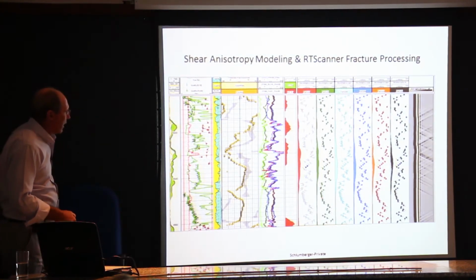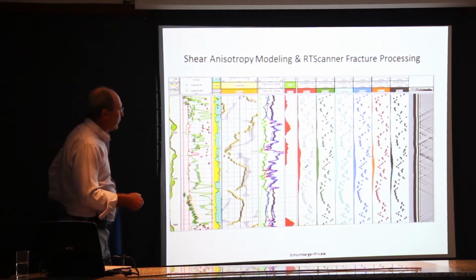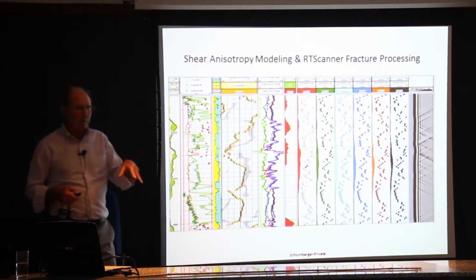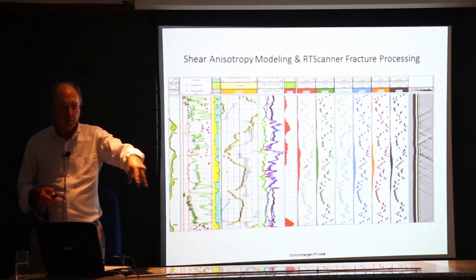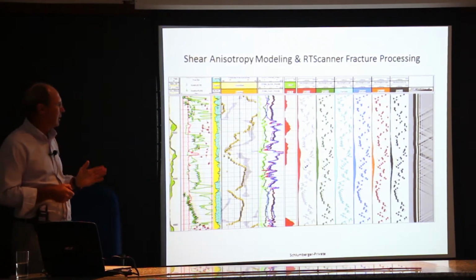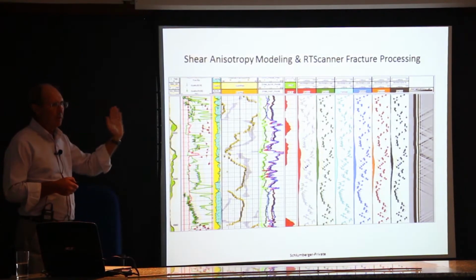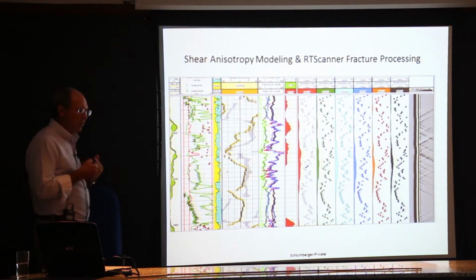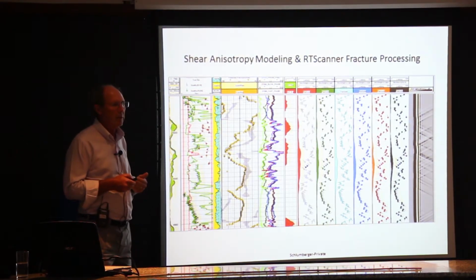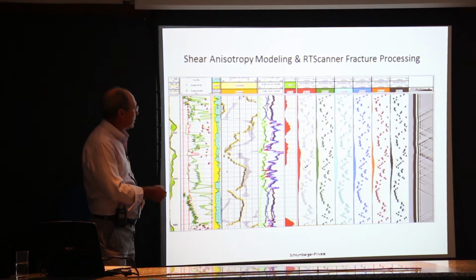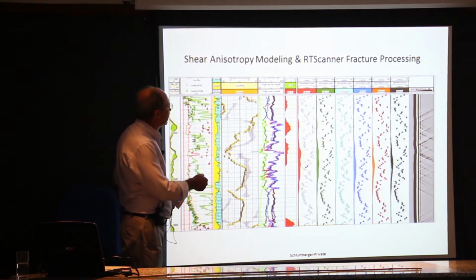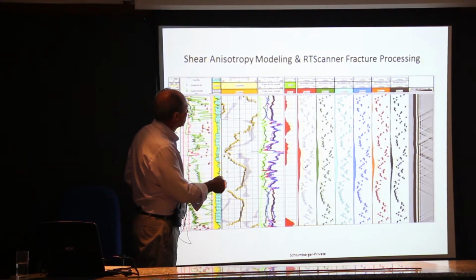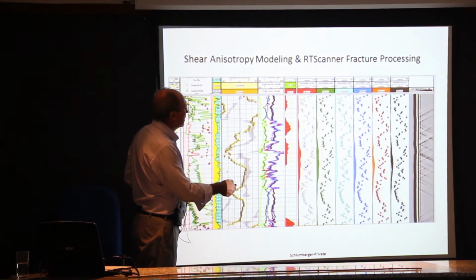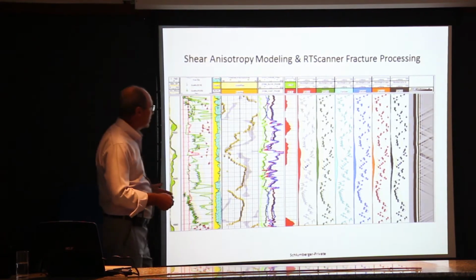And the next step is, if we combine this idea where it's called four-component rotation, where you rotate the fast and slow shear to get the ideal orientation of the true fast and the true slow, you can do the same thing with the 3D resistivity tool, and that's what we've done here. And with the resistivity tool, we start out with, I think this is about a 15-inch, and then we're moving to 20 inches, 25, 30. Finally, we get to about 50 inches deep into the formation.